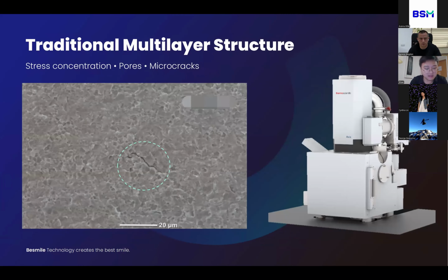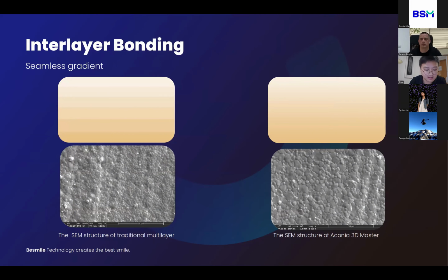We analyzed the conventional multilayer structure by using the scanning electron microscope. Non-uniform grains transition at the interlayer interface leads to stress concentration, pores, and micro cracks in the bonding region between adjacent layers, which is the root cause of the lower interlayer strength compared to the individual layers. We can see that these two pictures show the structure of the traditional multilayer and 3D Master under the scanning electron microscope.